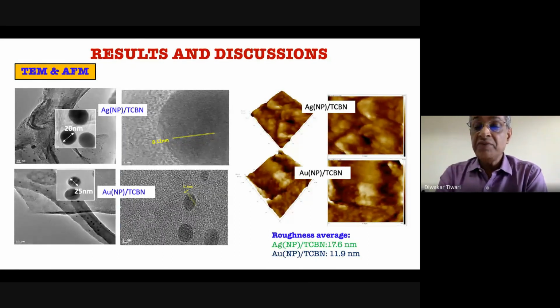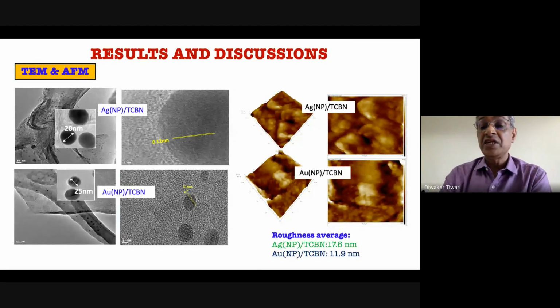At the same time, we have done the AFM. With the AFM data, we could get the surface roughness, which is an important aspect. We got 17.6 nanometers for the silver-based material, and 11.9 nanometers for the gold-based material, with the help of this atomic force microscopic data.